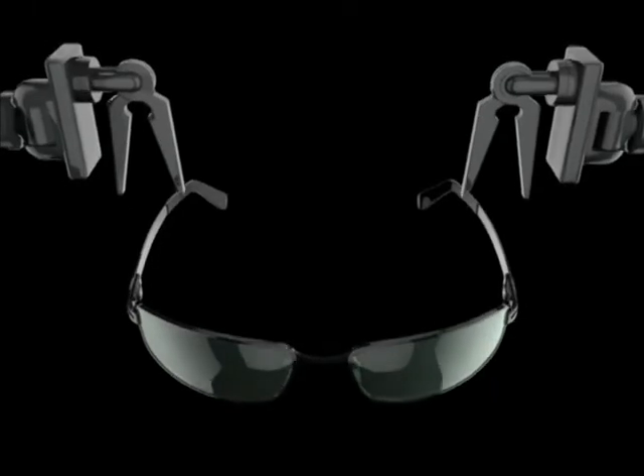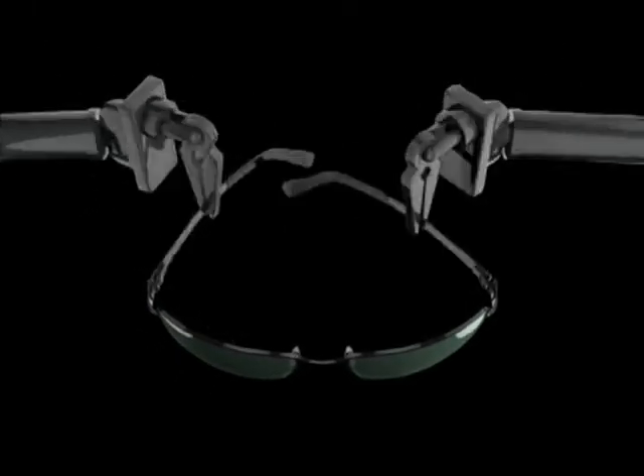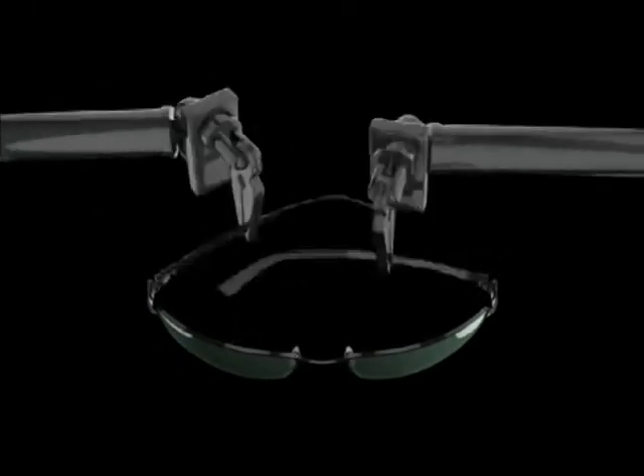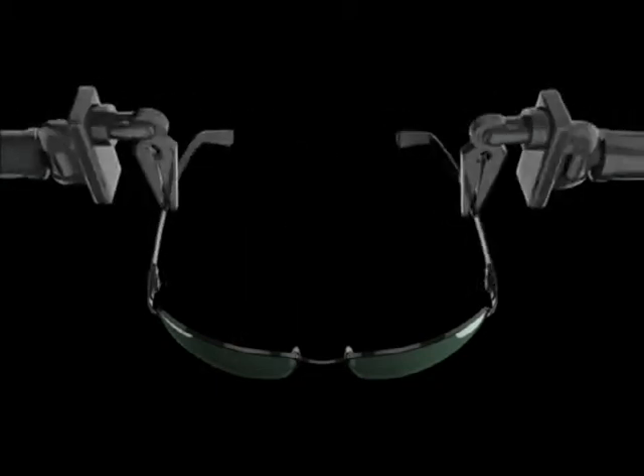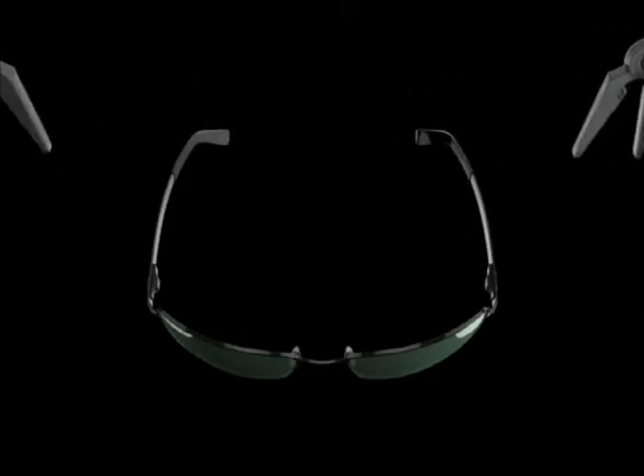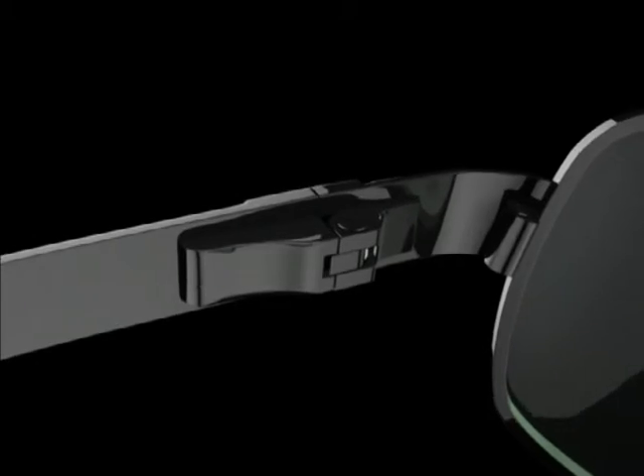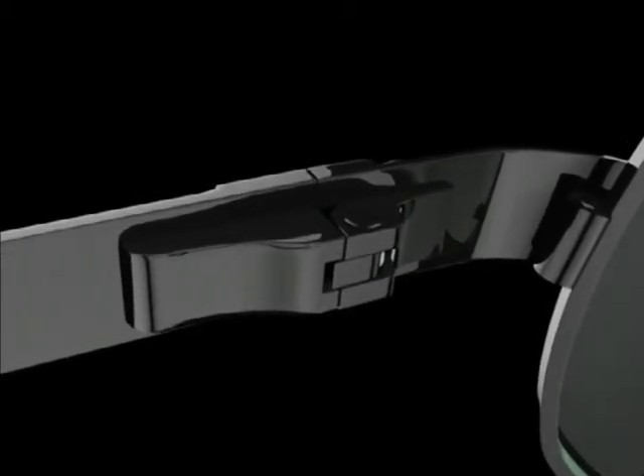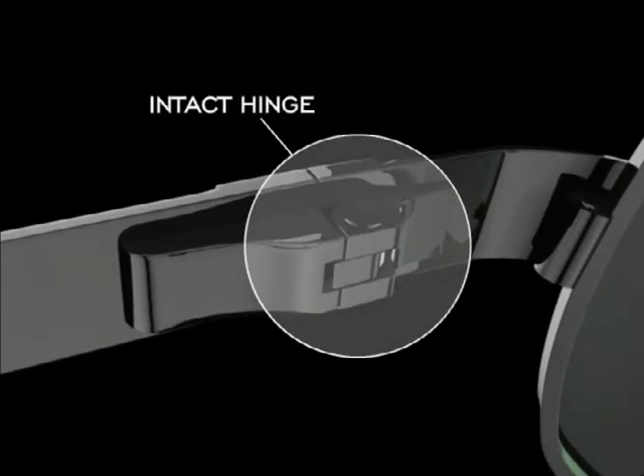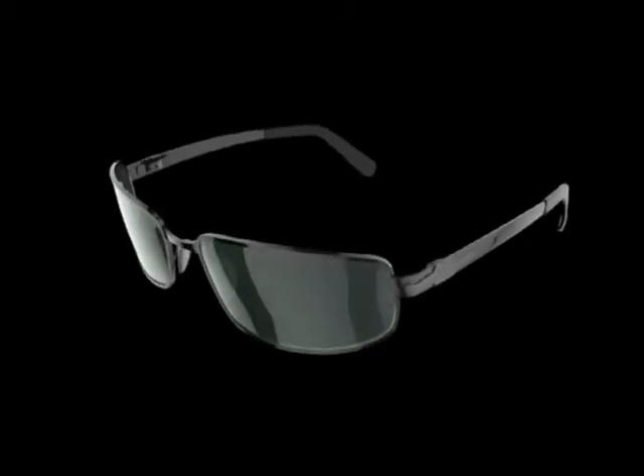Resistance to stress on the temple arm. This is an additional Luxottica test made besides the standard ones required by current laws. The temple hinge is the part most subject to stress on the frames. A temple arm must remain intact even after prolonged use. This test, which opens and closes the arm 25,000 times, simulates the normal functioning of the temple arm.